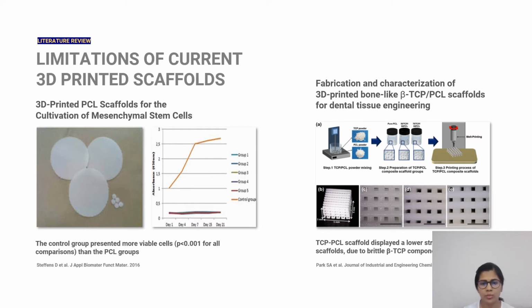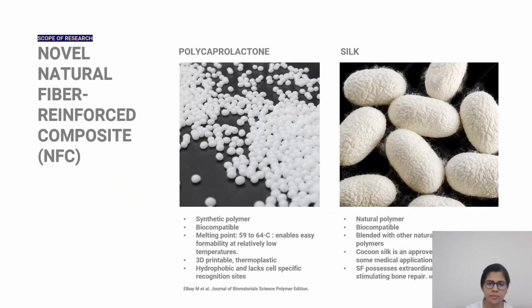Another group mixed PCL with beta tricalcium phosphate and 3D printed it. They could see good bioactivity, but at the same time, because of the brittle nature of beta tricalcium phosphate, the composite has shown less strength when compared to that of pure PCL.